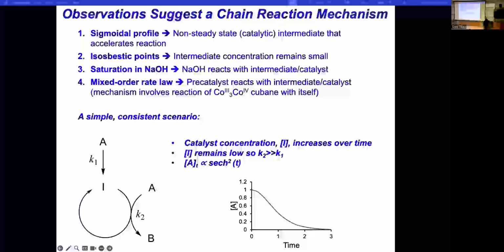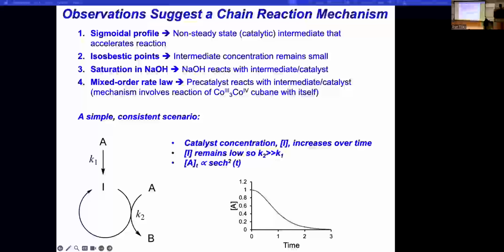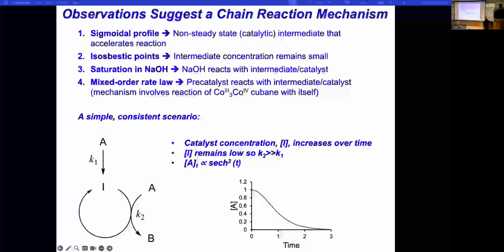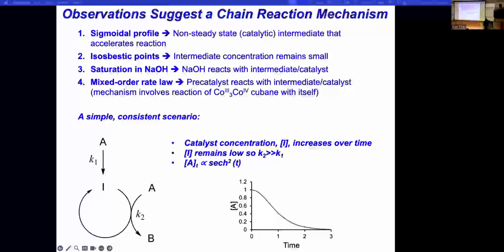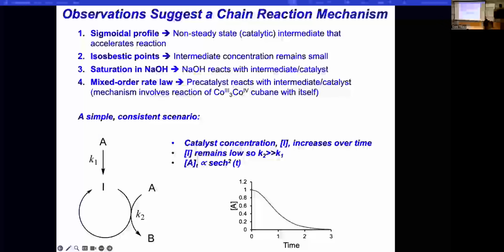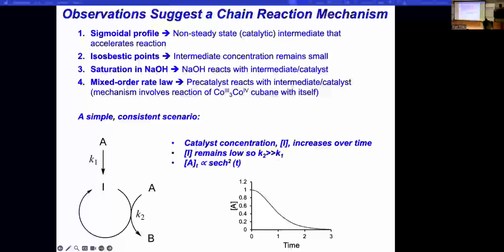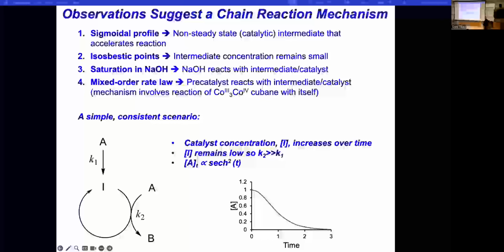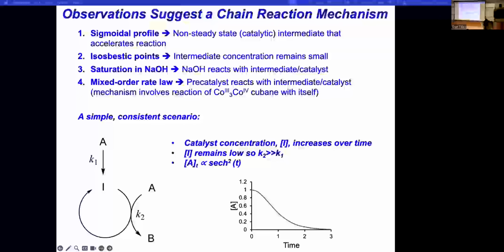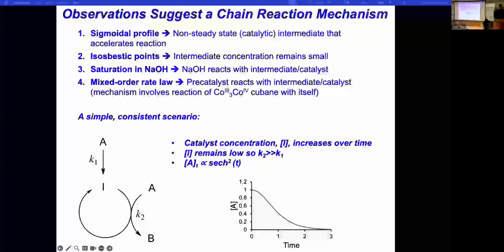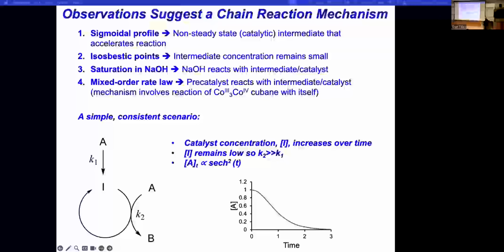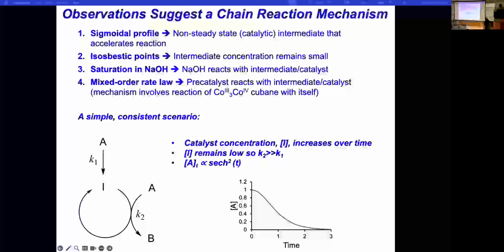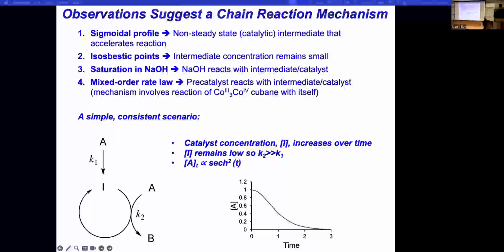So here are some of the observations on the kinetics that are taken together and what we think that means. So there's a sigmoidal profile for the concentration dependence, and that usually means you have some kind of autocatalytic or non-steady state intermediate that is involved in the reaction. There doesn't seem to be kinetic evidence for an intermediate building up. There's a saturation in hydroxide in the mixed order rate law. And putting all this together, it seemed to suggest a mechanism that you see here.